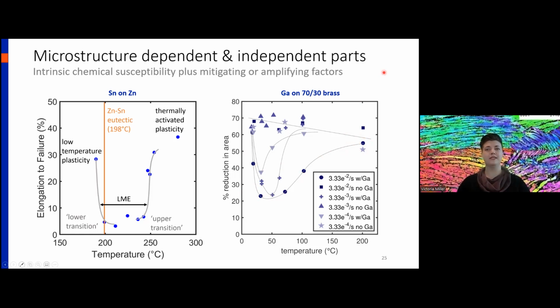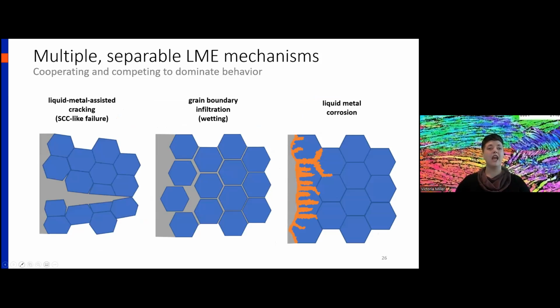The second half was that there were multiple separable liquid metal embrittlement mechanisms. And we propose a minimum of 3 mechanisms. There may be additional mechanisms that haven't been fully described yet. So the first mechanism that we propose is liquid metal assisted cracking. This is a lot like stress corrosion cracking, but in a liquid metal environment. The second mechanism we propose is grain boundary infiltration, or grain boundary wetting.